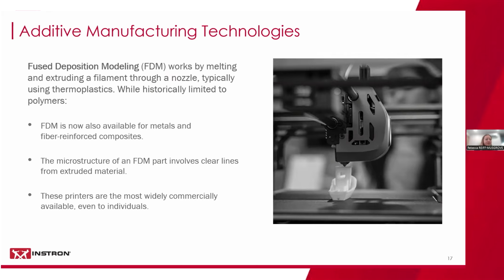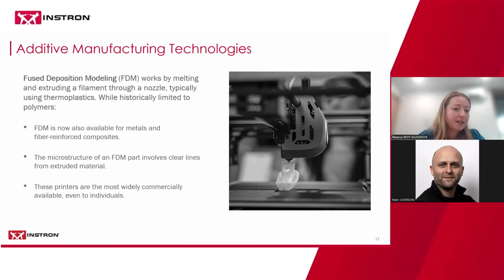That works by melting and extruding a filament through a nozzle, typically using thermoplastics. While it was historically limited to polymers, we can now also see it for metals and fiber reinforced composites. Recently I saw people printing metal powder in a polymer binder, and then they burn off the polymer binder to create that metal part. In terms of microstructure, we do end up seeing clear lines from the extruded material within the structure, which are potentially obvious structural weak points. And as I said, these printers are the most widely commercially available, and even many individuals have their own FDM printer as well.